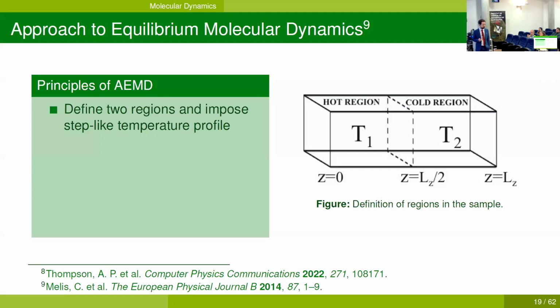So we have introduced a little bit of molecular dynamics, and to calculate the lattice thermal conductivity, or kappa L, we use a molecular dynamics technique called approach to equilibrium. It works like this. We define two regions in the sample and impose a step-like temperature profile, as you can see here in the picture. We define T1, for example, greater than T2. So we have a hot region of the sample and a cold region of the sample.